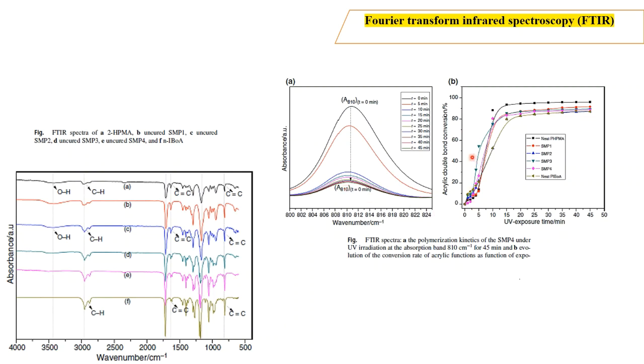However, the evolution of the conversion rate of the acrylic double bonds also confirms that all the systems show a very fast polymerization rate after 10 minutes of polymerization and start to saturate after 20 minutes. Finally, the highest conversion value, between 89 and 98%, means the total polymerization of all the acrylic monomers existing in the systems.